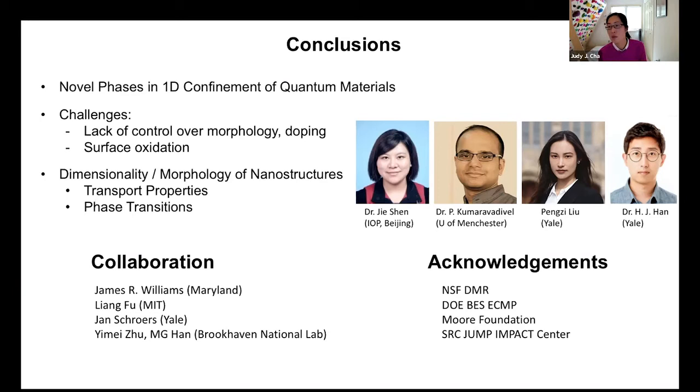For CVD growth, especially if it's chalcogenide materials, selenides, tellurides, you can do the overcoating with an amorphous selenium or tellurium layer. And that is actually really effective. All the thin film people, when they send samples to get the XPS done, would do the amorphous selenium or tellurium coating. I think that is still a very effective method. When it's other things like arsenides or phosphides, then I don't have an answer for those yet.